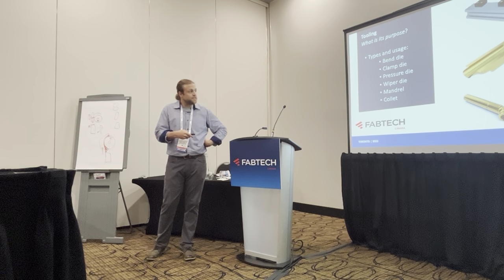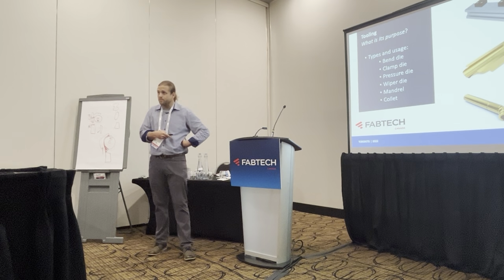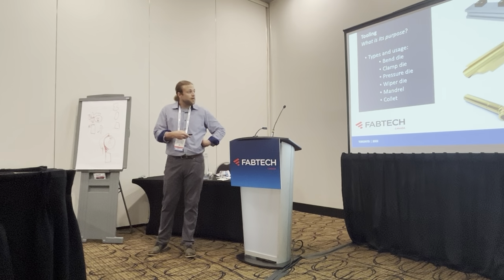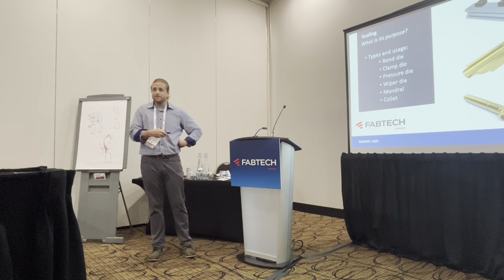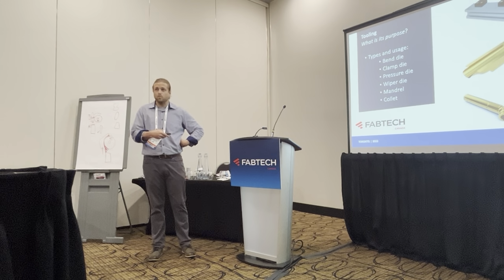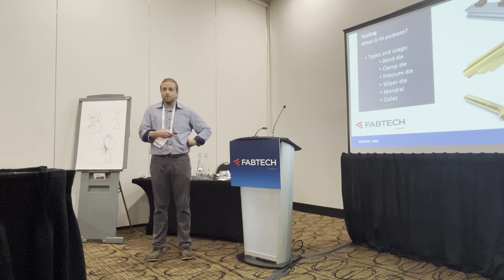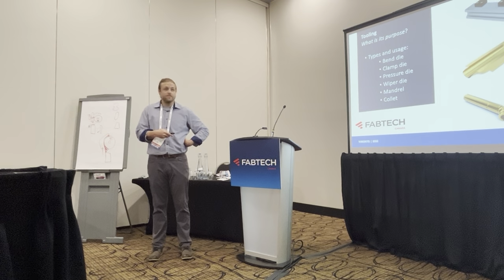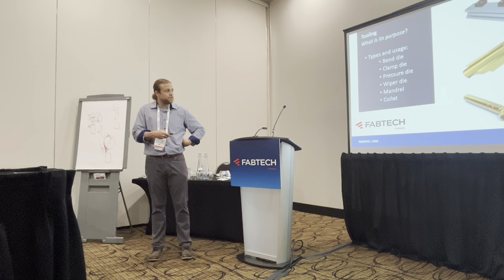But right here you can see this is a three ball mandrel, and this body is the shaft, and you can actually just bend off of this. If we didn't have these three balls on the end, this would be considered a plug mandrel. What you like to do is this tip, you want to have just past tangent point on the bend. There's a large math calculation to actually figure out the exact placement you would want. But there's a general rule where you can start 60 thousandths or so past, depending on what it is that you're bending. But you always want to put that nose just past tangent point.